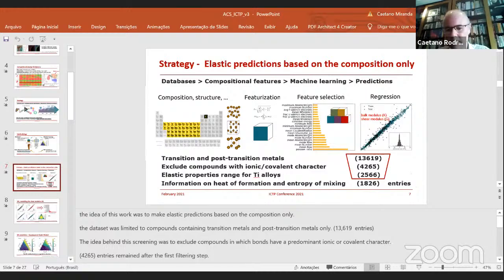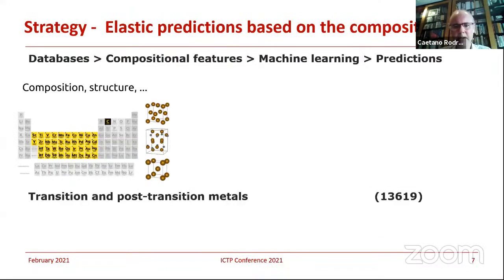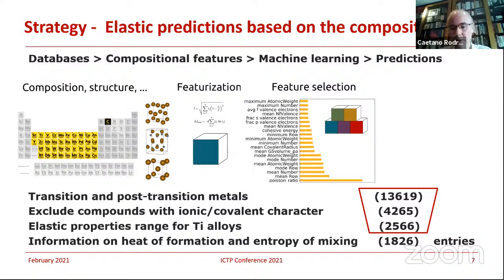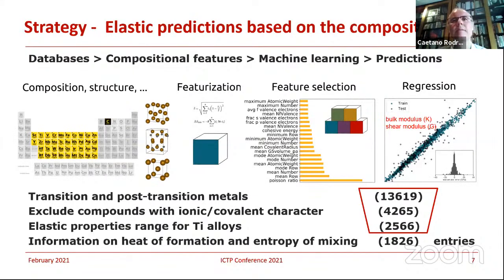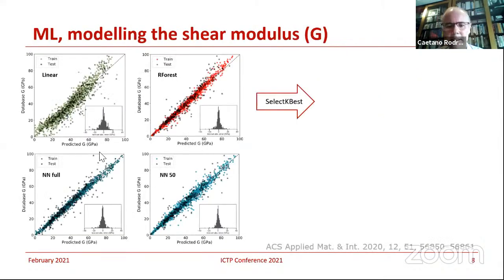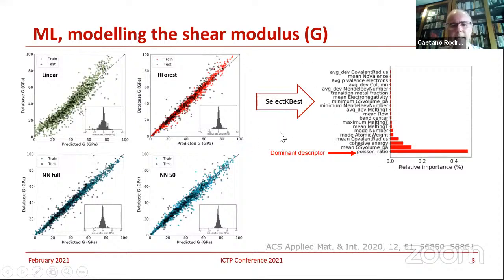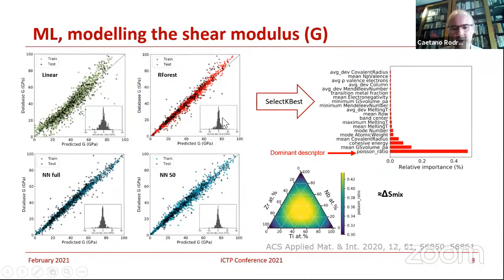So in this particular case, we used a set of around 550 features that were available for those materials. In this particular case, we used the scikit-learn library to make this selection. Now, regarding the random forest and the other methodology that we used, what we would like to see here is actually how robust this particular region that we are looking for was.